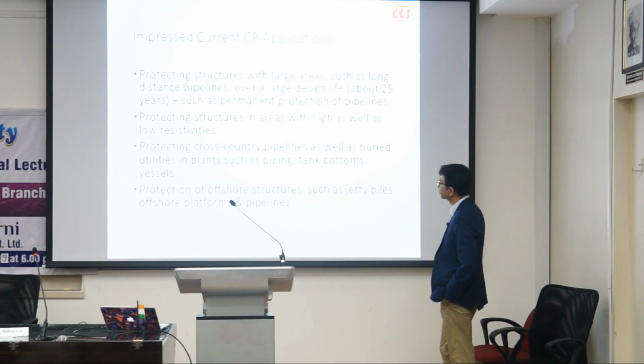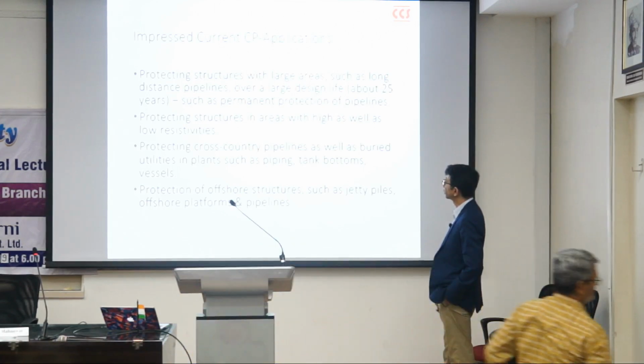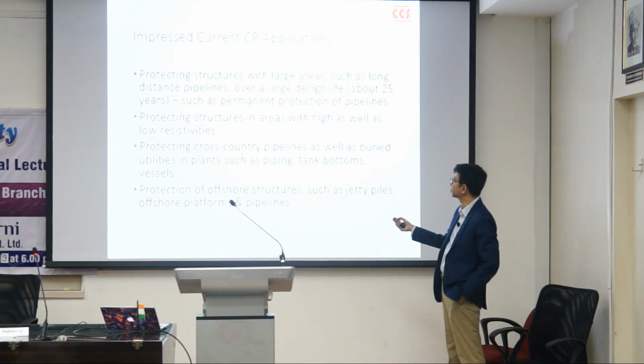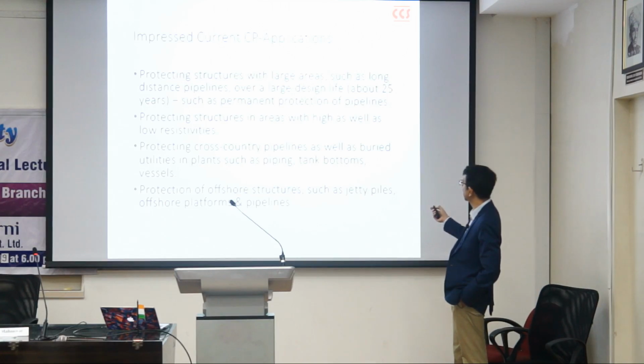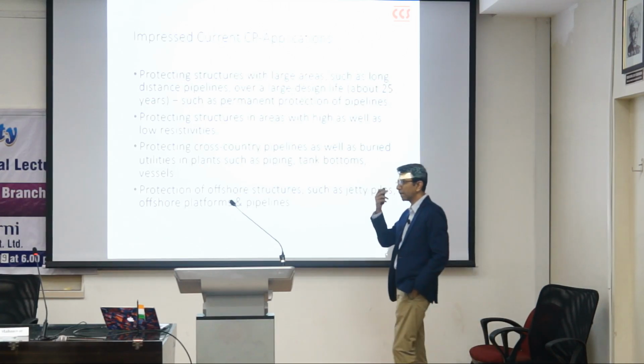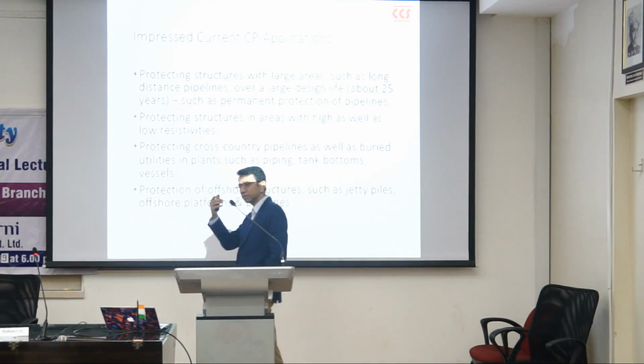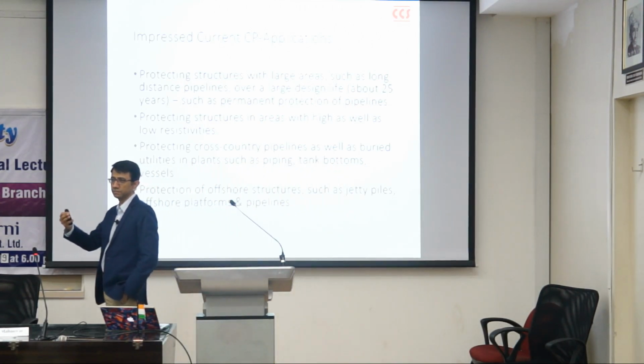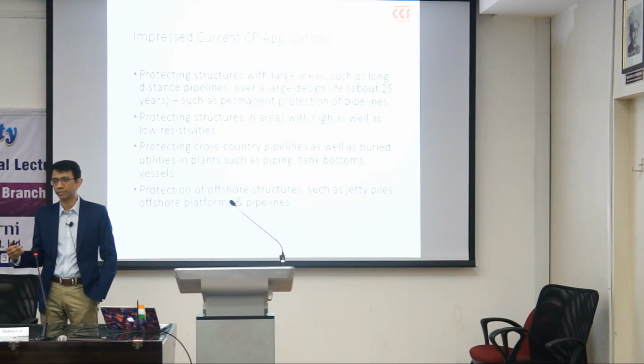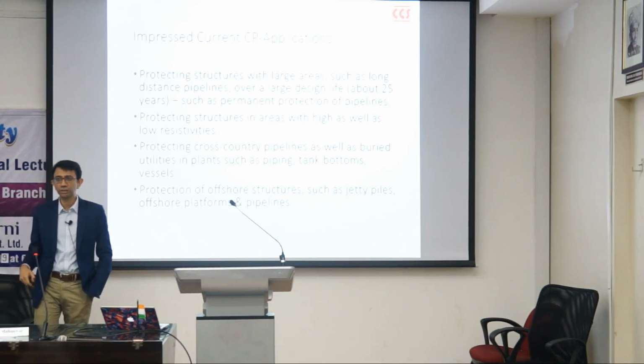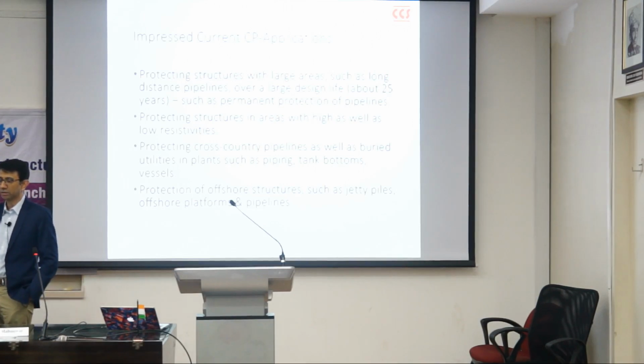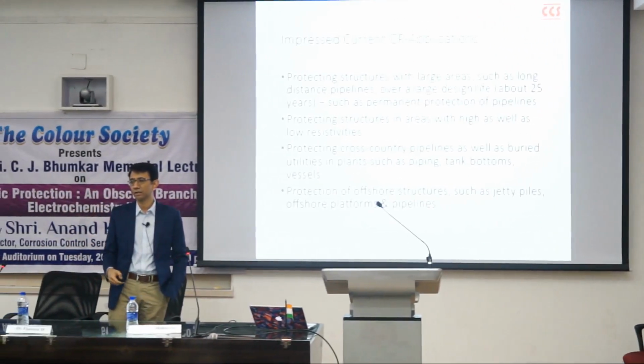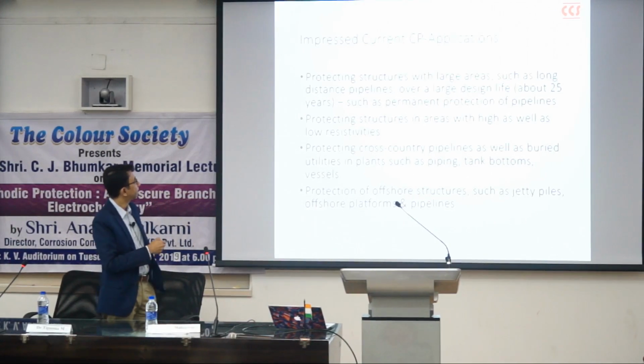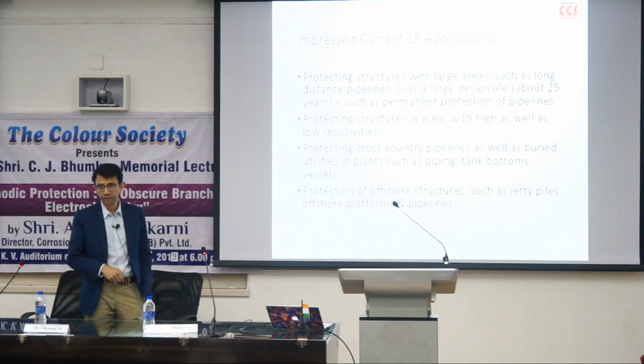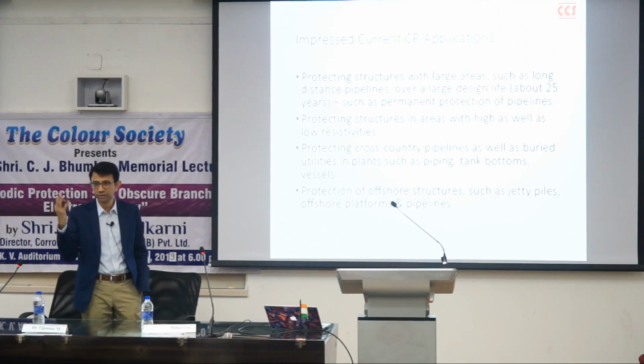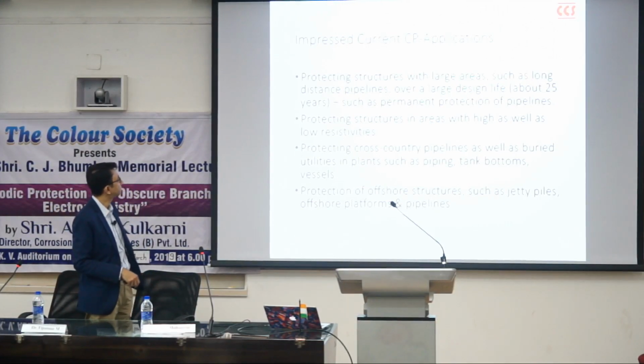So the applications flow from the features. Now you don't have the constraint anymore. Large areas can be protected. Design life can be more. So typically you use galvanic systems for the construction phase of a pipeline. So a pipeline takes 1 or 2 years to build. You use galvanic anodes for protecting the pipeline, and once it's completely built and commissioned, all the mechanical activities are completed, then an impressed current CP system comes into play, and that can be designed for 20, 25, 30, 35 years as the case may be.